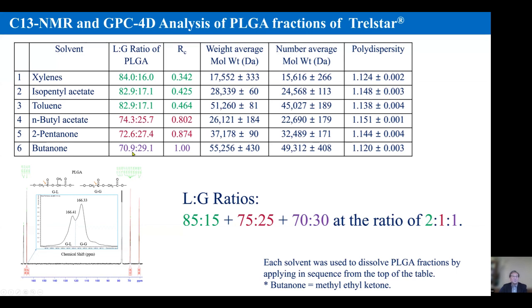Now the question becomes, how do you distinguish the LG ratio 73 from 71? The reason is that we measure the blockiness using NMR, and then you can see the groups. The first has a distinct blockiness of about 0.4, which is very different from the next one, about 0.85. And that is also different from blockiness 1. So we can confidently say there are three different types of PLGA present in the formulation. In the end, we conclude that there are three different LG ratios: 85-15, 75-25, and 70-30.